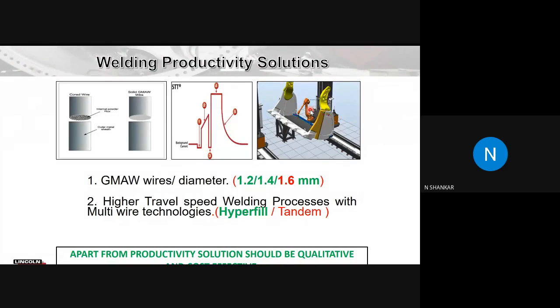So when you look at means and ways of increasing your productivity, people normally talk about using larger diameter wires. For example, if I'm welding with a 0.8 mm wire, I can move to 1 mm wire, then to 1.2 mm wire, then to 1.6 mm wire. That is where GMAW ends. But some customers, some industries, have started using 2 mm wire for the GMAW process. They assume that by increasing the wire diameter, you will deposit more. The other way is to have two wires together welding in one single arc. This is multi-wire systems. So these are ways and means of increasing deposition.